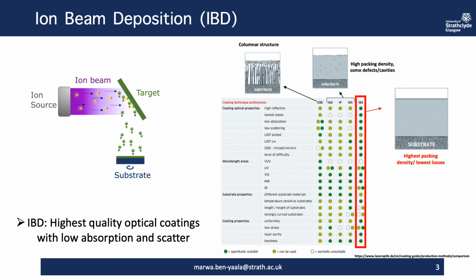So what is particular about this technique? In this table I included a comparison between the different deposition methods, including electron beam evaporation, ion assisted deposition, ion plating, and magnetron sputtering. As you can see, the IBD is the method that produces thin films with the highest packing density, the highest quality, and the best optical properties, including lowest losses and low absorption and scattering.